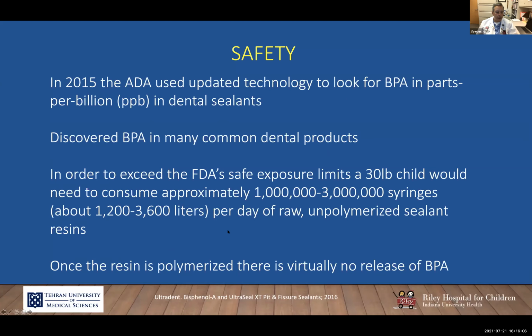In 2015, the American Dental Association updated the technology to look for BPA in parts per billion in dental sealants. They found BPA in many common dental products. Now, the Food and Drug Administration places a maximum amount of BPA. So in order to exceed the FDA safe exposure limits in a 15 to 18 kilo child, you would need to consume about 1 million to 3 million syringes per day of raw unpolymerized sealant composites. So clearly, in order to provide an amount of BPA that would cause toxic effects in the child, you would need to give between 1 million and 3 million syringes of raw unpolymerized sealant composites. Once the composite is polymerized, there is virtually no release of BPA.